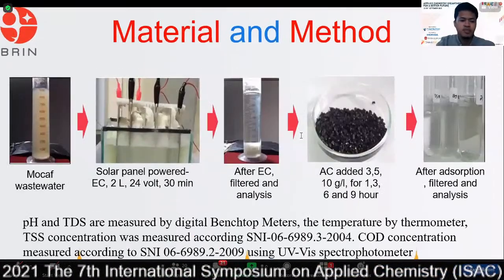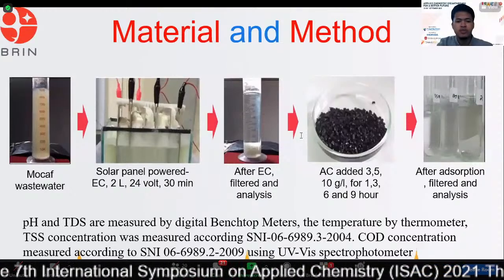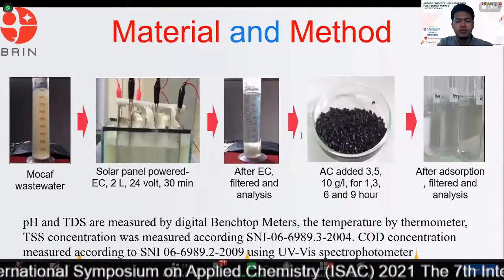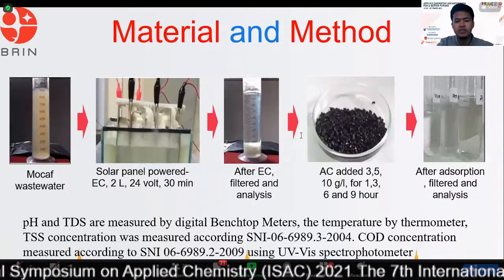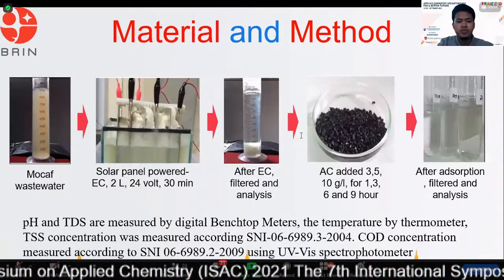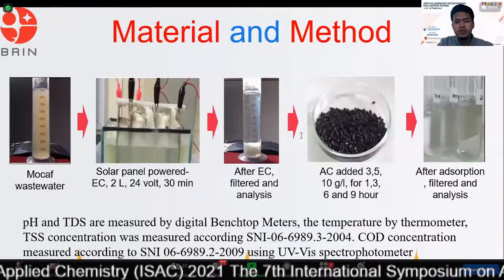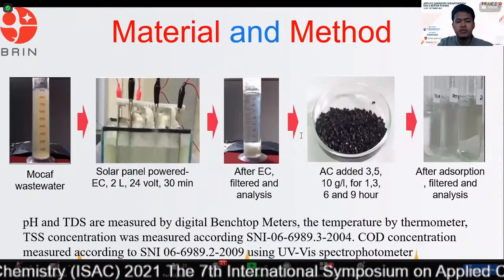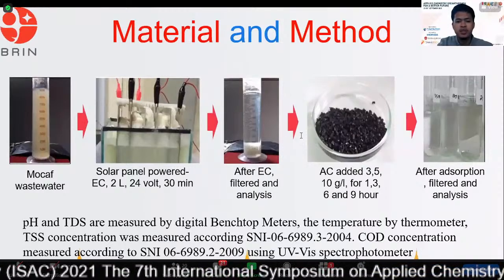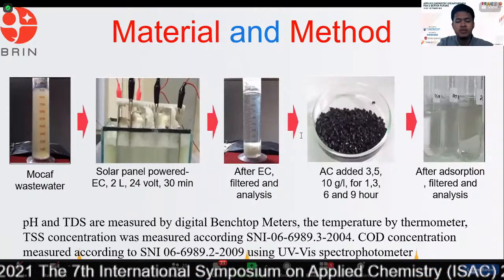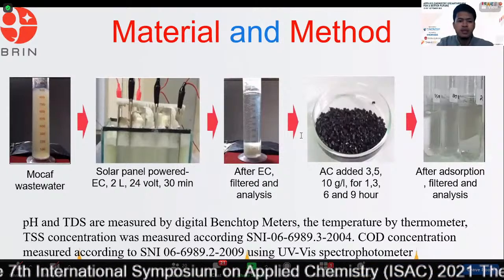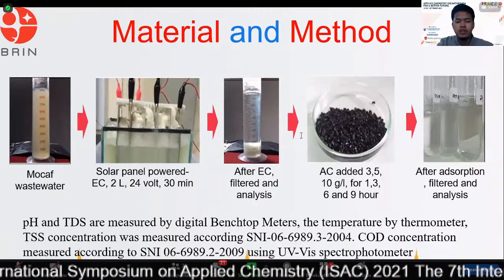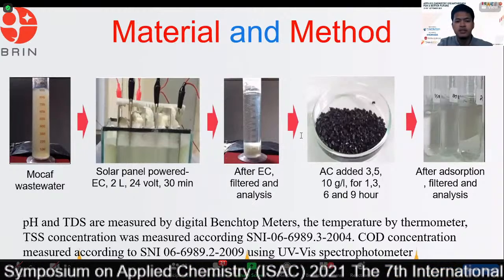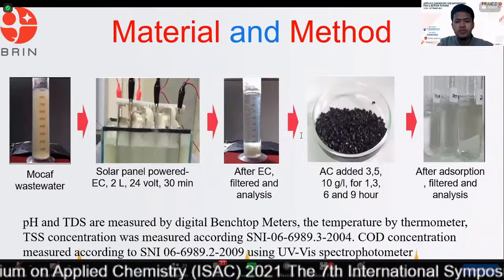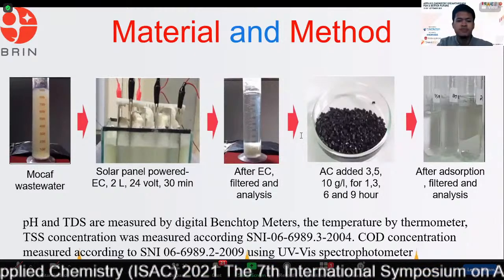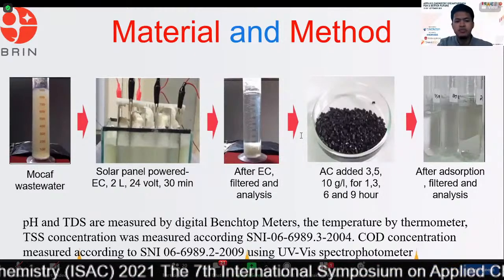These are our materials and methods. We collected MOCAF wastewater from a small and medium enterprise in Bogor, West Java, Indonesia, and we measured the composition. After that, we treated it with electrocoagulation. The chamber is a glass reactor with a capacity of 2.5 liters. The electrodes that we use are aluminum, and the distance between electrodes is 3 centimeters. We use electricity from a solar panel.